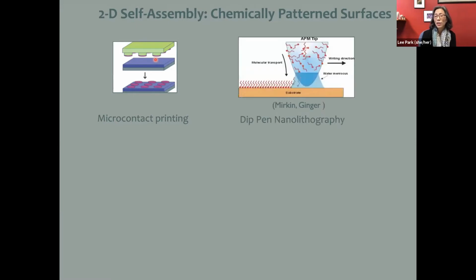Another possibility is a technique known as dip pen nanolithography. In this technique, you take a very fine tip that is atomically precise at the end, and you dip it into one of these molecular inks, and you can use it just the way you would use a quill pen. That is, the ink will flow off the tip and onto a surface. And again, your ink is one of these amphiphilic molecules. So as it flows off the tip, it adheres to the surface in a very regular way. Using this method, you can actually write patterns onto a surface that are one molecule thick and where your lines might be a few nanometers in width.